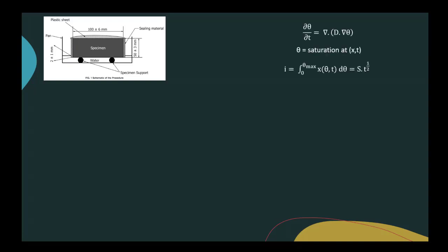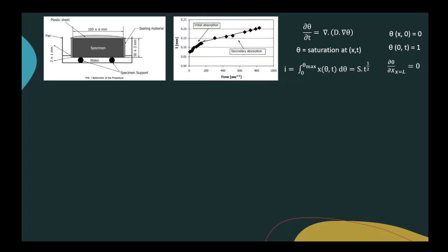And then this is the one-dimensional diffusion equation. Knowing the initial and boundary conditions, like the sample is initially dry, the saturation is 100% here, and the flux or flow rate on the top is 0, we can estimate penetration or cumulative absorbed water as a function of the square root of time. S is the slope of this line, which is called sorptivity. If the S value is higher, that means our matrix is porous. That means it's more thirsty to absorb water rapidly.